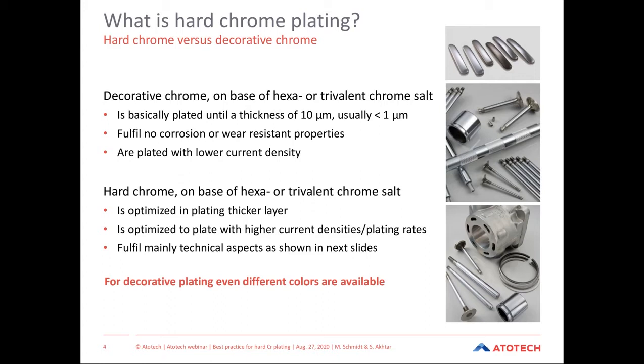Chrome plating comes in two forms, and this is decorative plating and hard chrome plating. Decorative plating, as the term suggests, is all about achieving the best possible cosmetic finish on the component. Here, the chrome layer is applied on top of copper nickel coatings and serves no other function than to produce a bright finish. It has no significant impact on improving the wear or the corrosion resistance of the substrate, and is typically plated to 1 micron thickness for the bulk of the decorative applications. Nowadays, the chrome can be plated in other color finishes other than the traditional bright blue.